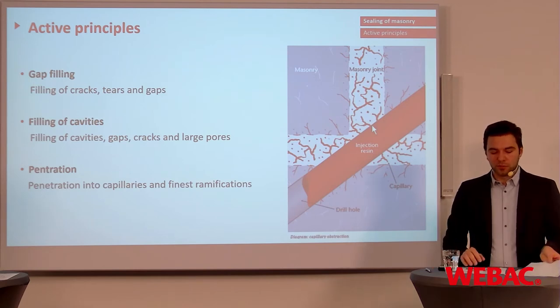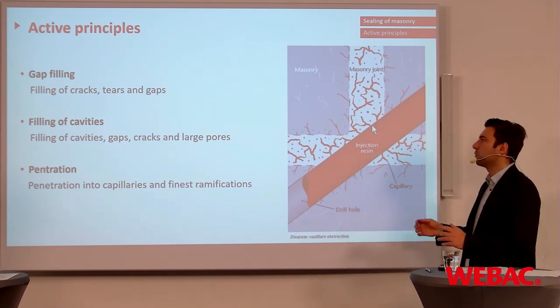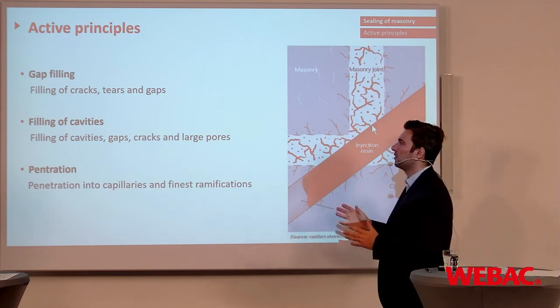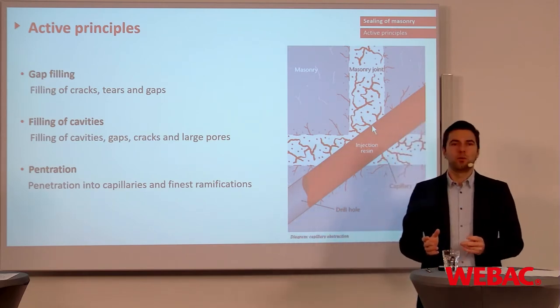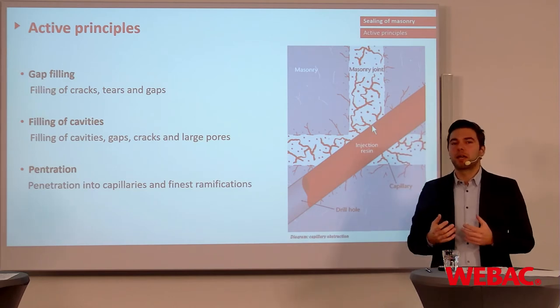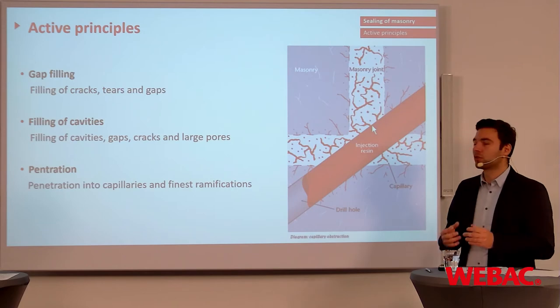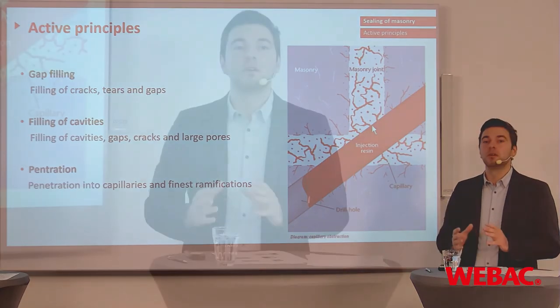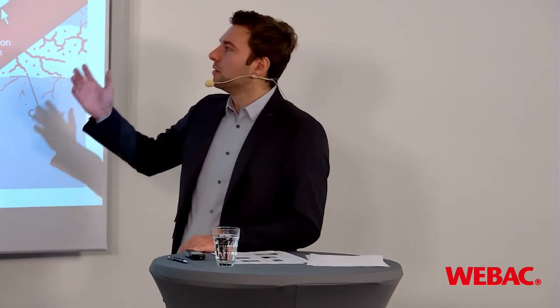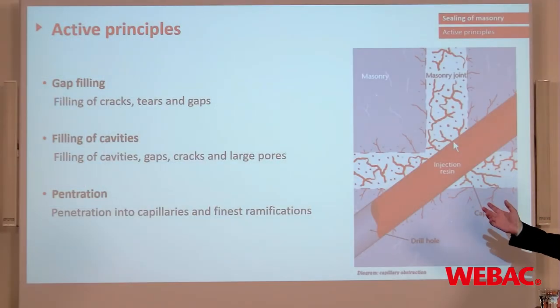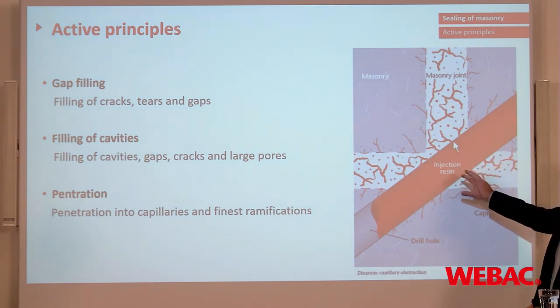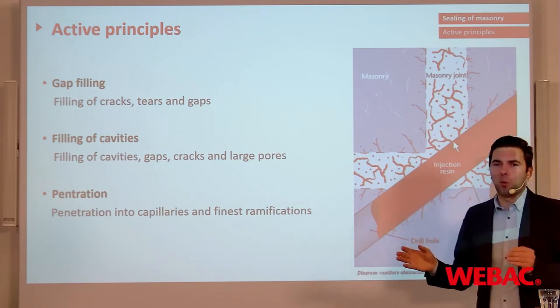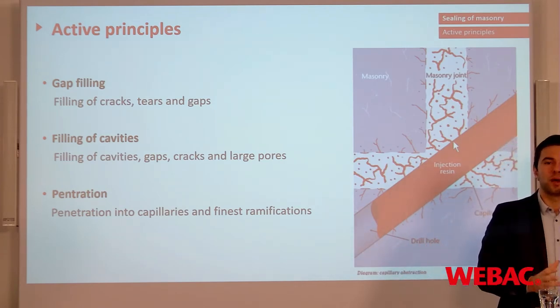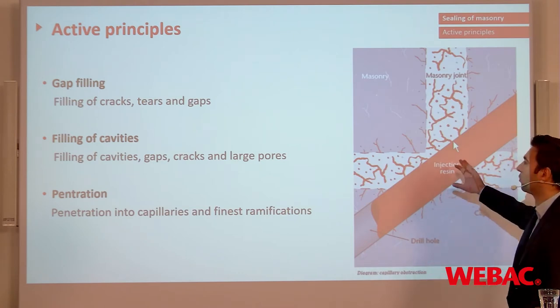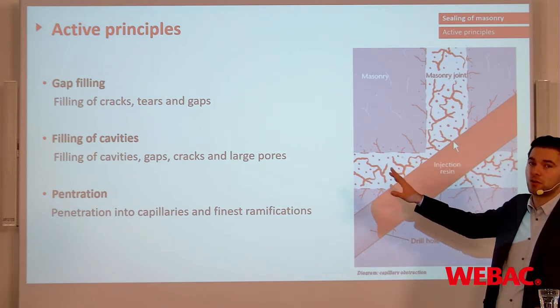So now we're coming to the active principles, and in general we are going to achieve three targets. The first of all is gap filling. What do we mean by gap filling? By gap filling, we mean that we are going to fill cracks inside the joint structure or even the stones. Tears and gaps have to be filled. Filling of cavities. You never know how the cementitious joints are, in which kind of conditions, or even if you have hollow areas in your stone. So therefore, it's also important to fill up these cavities inside your structure.